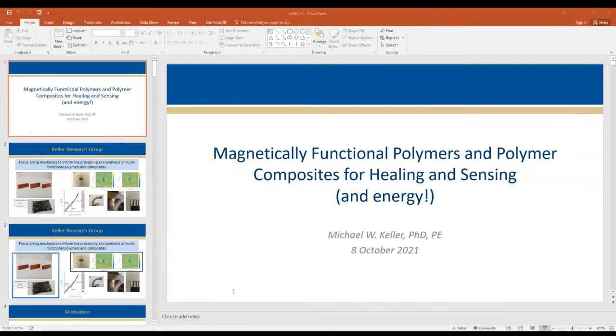There's a large motor diaphragm here, which is a polyurethane elastomer or semi-rigid polyurethane material. There's a pilot membrane here, right? If either of these get damaged, you now have a direct vent to the atmosphere, right? And so our goal was to use a microcapsule or microvascular approach, and I'll focus on a microvascular approach, to create a self-healing membrane to go in there to seal up any damage, right? So what happens is it flexes and you get a crack or a tear, right, in your membrane material, and then suddenly you're venting.